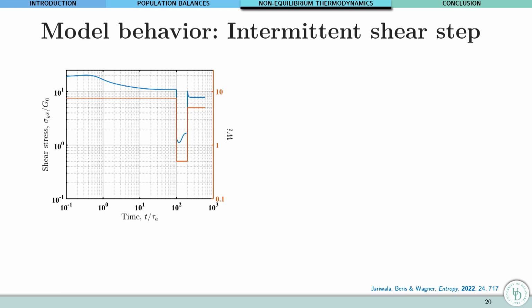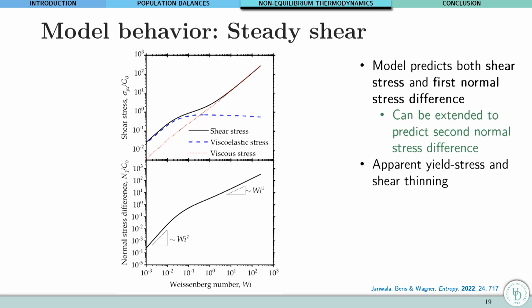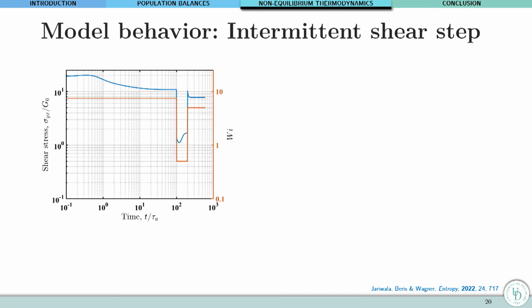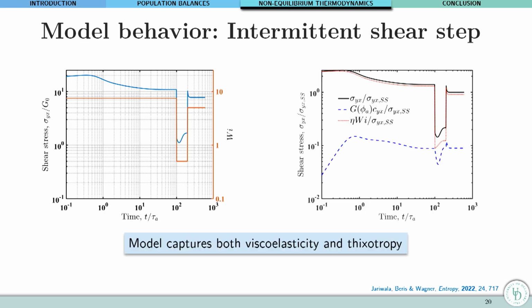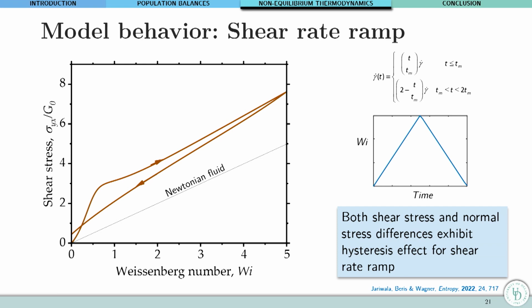but we describe very important effects that you couldn't get otherwise, genuine non-Newtonian effects, as for example, normal stresses that grow like the Weissenberg number at high Weissenberg numbers. Forget these low shear rate regime, which is just outside the window that we fit. We only try to fit this part. And then we were able to also describe transients, and I will go very quickly because I don't want to take too much of your time. Also show this hysteresis phenomena.